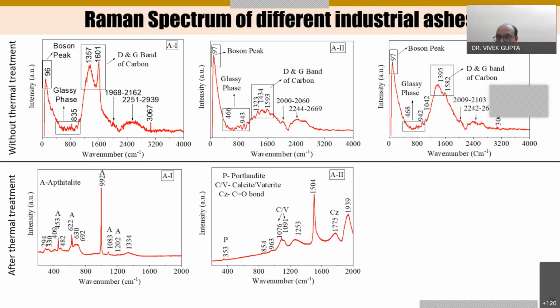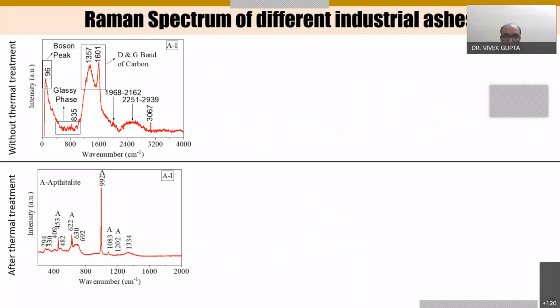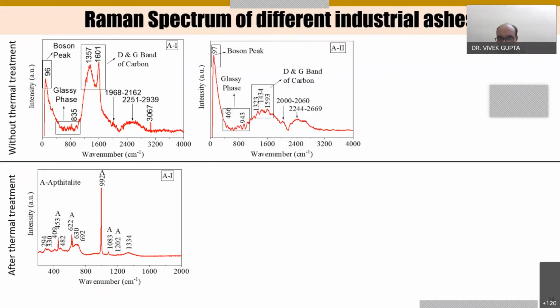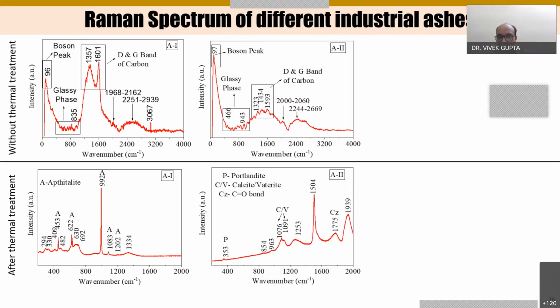So what we have done, we have used a novel methodology: we have analyzed the phases after treating them at 1000 degrees Celsius, and by comparing, you can see in the A1 ash the minerals are not very clear, but when we treated them at 1000 degrees Celsius, we could identify the aphthitalite mineral very easily in the treated samples. Similarly, in A2, we could identify the portlandite, calcite, and CO bonds in the thermally treated samples.